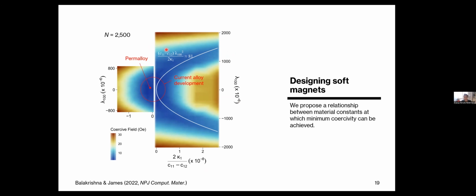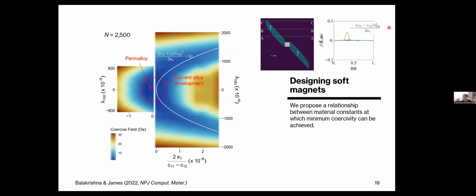Although we first discovered this quadratic relationship by doing simulations, the theoretical explanation comes from going back to your micromagnetics energy, non-dimensionalizing the different energy terms, and measuring which of these terms has the largest energy barrier just before your needle domain grows abruptly, loses its stability and rotates. You see that the majority of the energy barrier is coming from the energy term controlled by this parameter.